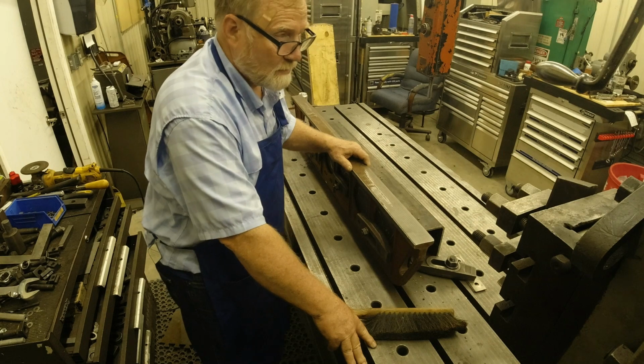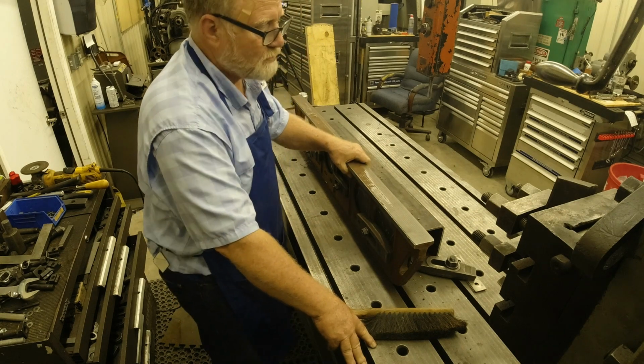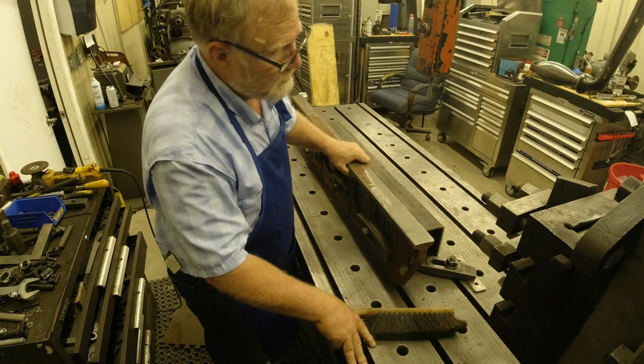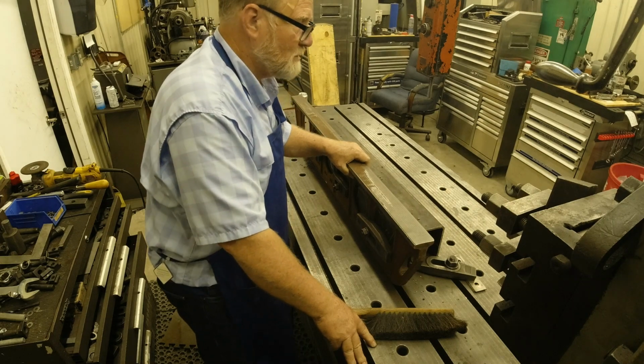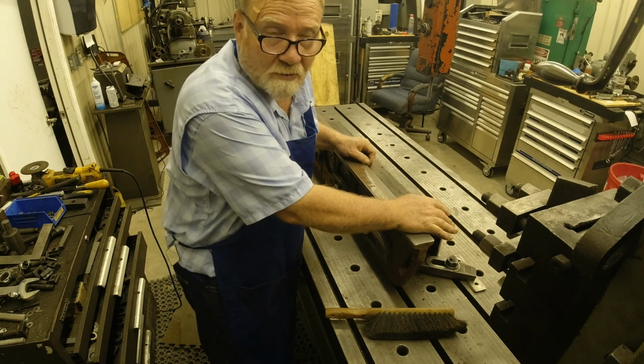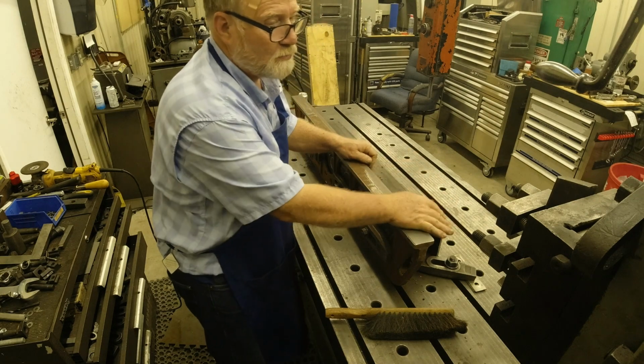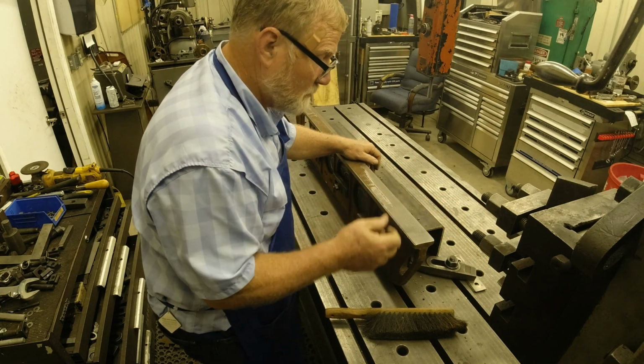It's always been a battle. You know, they used to say, well, we leave our castings outside for 10 years. They're naturally stress relieved. Or we ring them. Or we take it to 400 degrees. Or we do this. Or all kinds of witches' magic potions. As far as I know, the U.S. Navy was the first one to do a study to actually test all those methods. I'll put a link in the description to that paper on it.